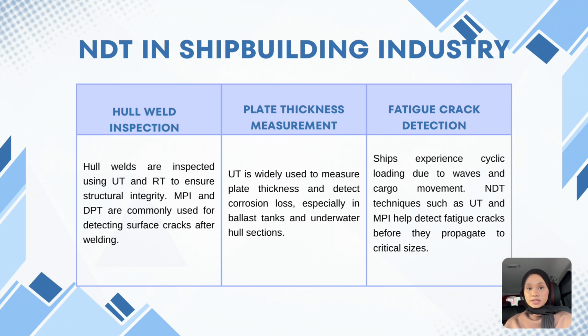Ultrasonic testing is widely used to measure plate thickness and detect corrosion loss, especially in areas like ballast tanks and underwater hull sections where corrosion is more severe. The last application is fatigue crack detection. The ship will experience continuous cyclic loading due to waves and cargo movement, and over time, this can cause fatigue cracks. NDT techniques such as UT and MPI will help detect these cracks at an early stage before they grow to more critical sizes and compromise the ship's safety.